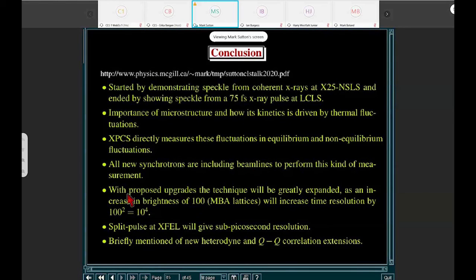The other thing I didn't emphasize, but I'd like to point out, is that these new MBA lattices at the APS will give a 100 times more coherent beam than current coherent beams. And the LCLS is even more exciting because it's going to be of order 1,000 times brighter than the current beams at the third generation synchrotron.